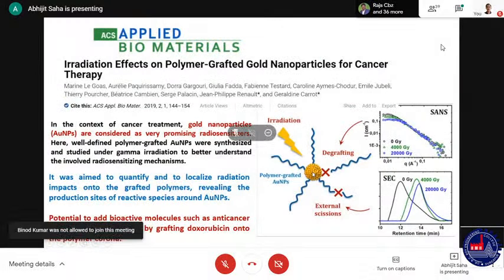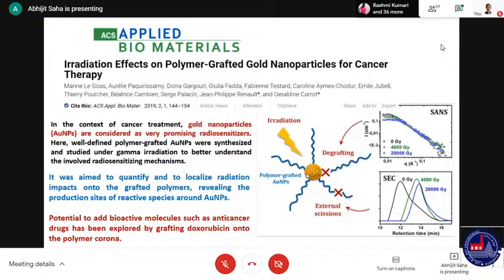Because when the radiation falls on the gold, the radiation does not directly kill the cell. It is first absorbed by the gold particles, which generate secondary species, and those can actually kill the cancerous cell. So if the gold particles are very selective and can selectively bind with the cancerous cell, then radiation will fall onto the gold particles, and those particles will only damage the cancerous cell, not the other normal cells. That is the objective of developing this kind of materials.